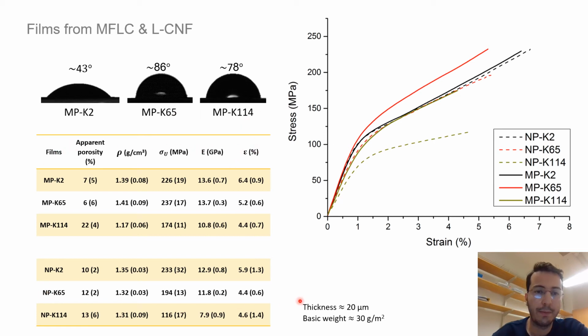And you can see apparent porosity, which is calculated back from density, and the ultimate tensile strength, modulus and strength of the films. You can see tensile curve of MP kappa 65 and MP kappa 2. They are almost as strong as each other, with ultimate strength about 230, 240, and their modulus is also quite the same, but for the micropaper with kappa 114, you can see that this is a little bit weaker. One reason is related to higher amount of porosity we have in this structure.